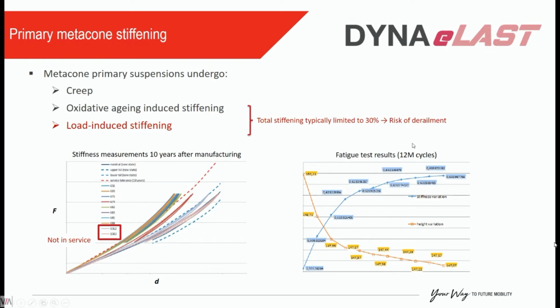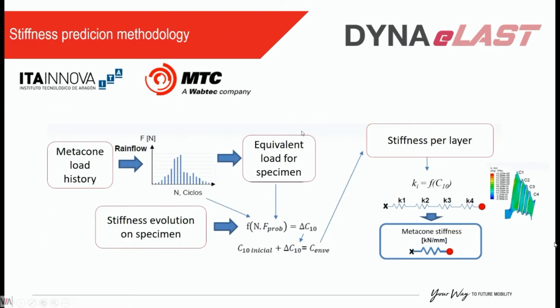If we look at a fatigue test of a different element, we see how the stiffness increases as the number of cycles increases, and we see how the creep also increases. The primary settles further and further. So we think it's a combined effect, and we need to deal with it. We need to limit the total stiffening to a 30% maximum because otherwise we will have a massive risk of derailment. And this, of course, constrains the design.